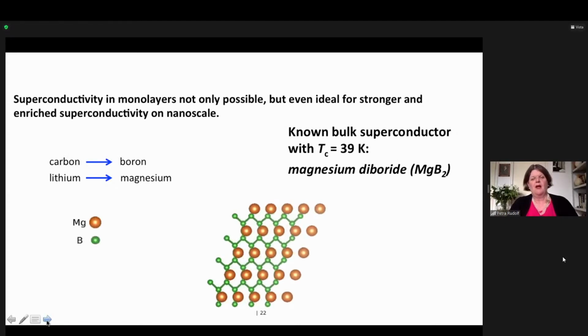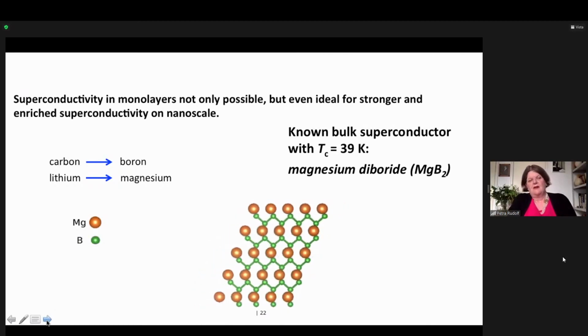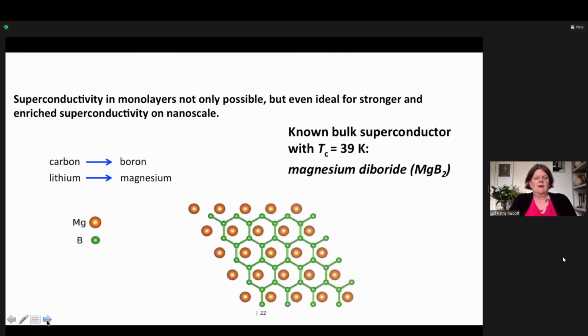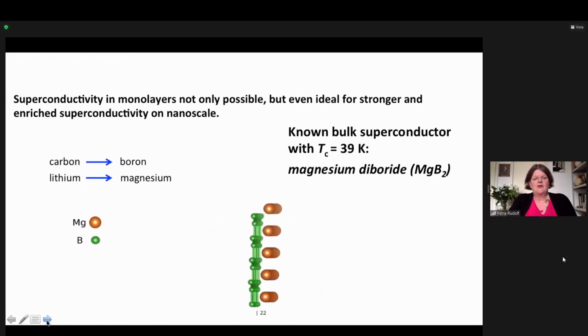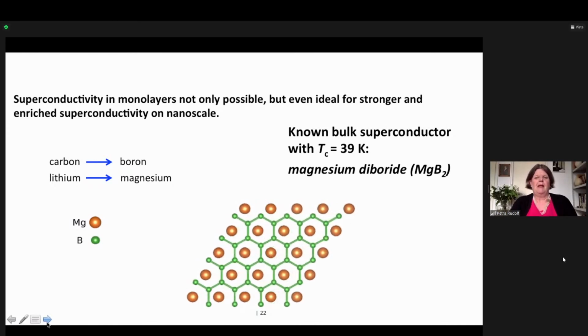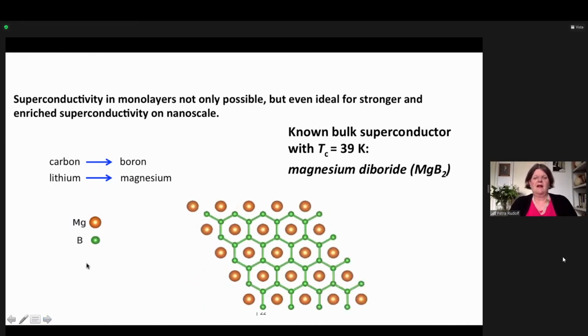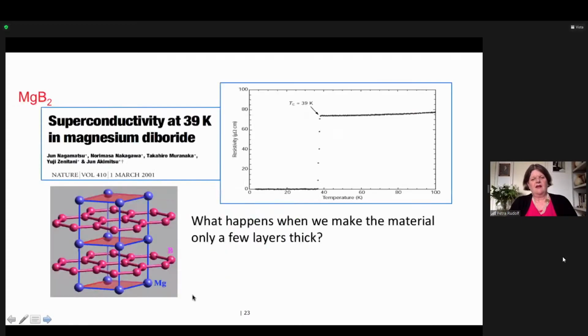For this material, you can also use something different. Instead of using carbon and alkalis or carbon and lithium, you can use magnesium and boron, and you get magnesium diboride. And you can think that this is superconducting in the bulk. In fact, it has a transition temperature at 39 Kelvin. And you can ask yourself what happens. This is also a layered material, so you can make it very thin, only a few layers thick. Is it still superconducting?